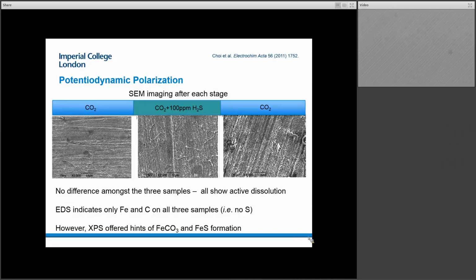One of the things that's particularly interesting is that they did SEM imaging on their materials at the conclusion of every stage. And one of their findings was, in fact, for this particular set of experiments, that none of the samples look demonstrably different. And moreover, they all show active dissolution, and EDX didn't really indicate any sulfur in that intermediate sample, really only iron and carbon, which is somewhat challenging. And so if they'd only looked at that surface analysis, they might have been surprised, right, that nothing had happened with the introduction of H2S.